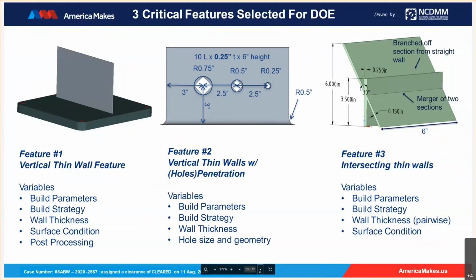For feature 2 and 3, it's basically a convolution of the thin wall feature with a second feature, i.e. the holes or the intersection. So we had to add on things like hole sizes, the hole geometries, and also the intersecting wall thickness, which is intersecting at a constant angle of 30 degrees with respect to the vertical wall itself.